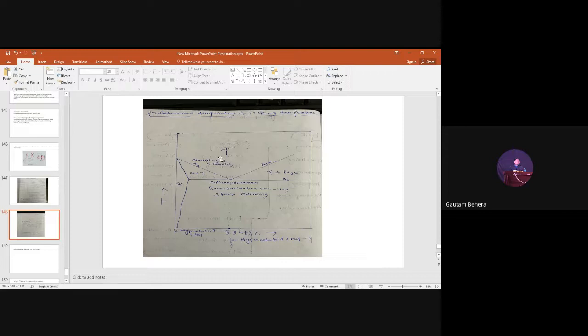So if you want to do normalizing and annealing of steel of 0.8 weight percentage of carbon, this is the composition 0.8, then the transformation temperature is what? It should be above A1, like 40 to 50 degrees above A1. This is the A1 line. That means 40 to 50 degrees above the lower critical temperature, if you want to do annealing or normalizing.